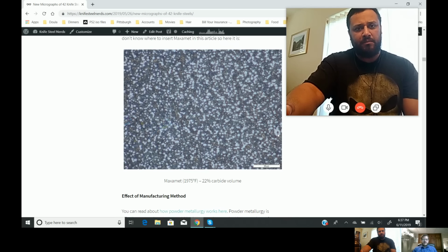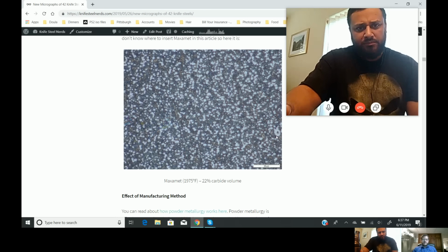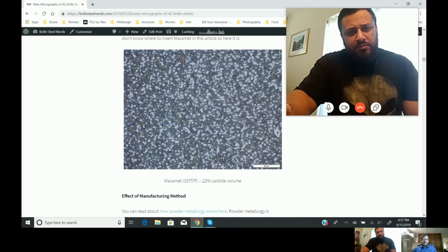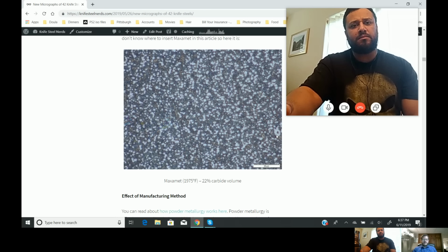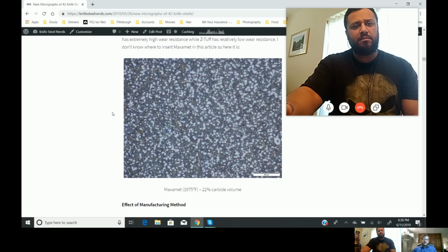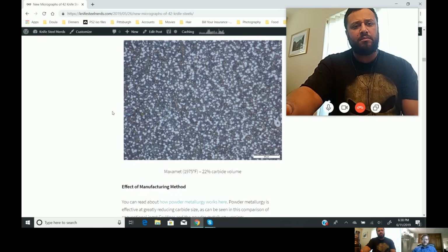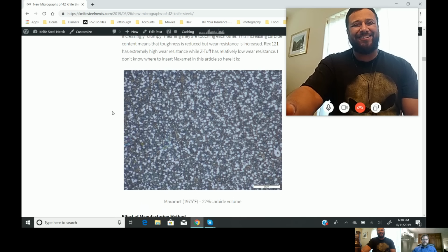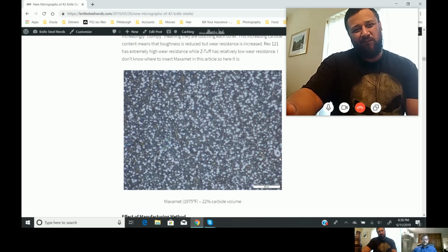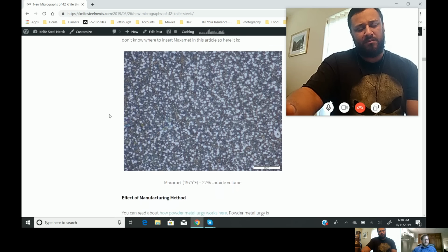The black spot in the middle is probably some kind of high temperature formation product, maybe an oxide or some kind of nitride that formed at high temp and then acted as a nucleation site for the carbide to grow. So it forms first and gets bigger. I can't think of a better way to explain that without using a lot more words. But anyway, that's what it is. Apart from that one spot, it looks pretty fine, at least equivalent to 15V, if not finer, to my eye.